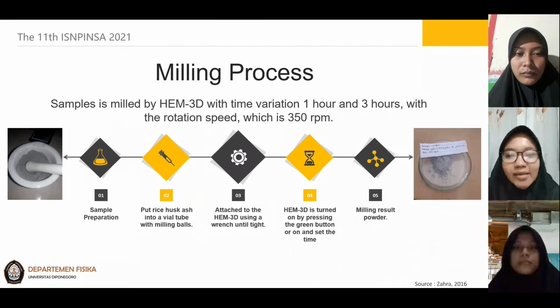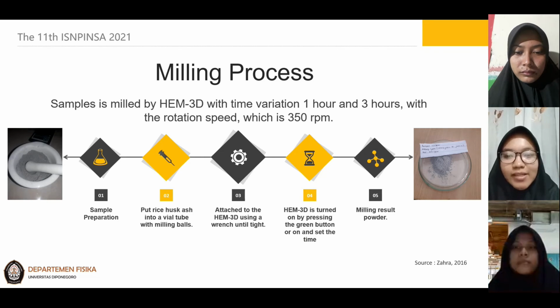Milling process. The sample is milled by HEM 3D with time variations of 1 hour and 3 hours, at a rotation speed of 350 RPM. The first step is preparing the sample. Then, put the sample into the vial tube with milling balls. Attach it to the HEM 3D using the wrench until tight. Then, HEM 3D is turned on by pressing the green on button and setting the time. Finally, the milling result is ready to use in the next step. Next slide.